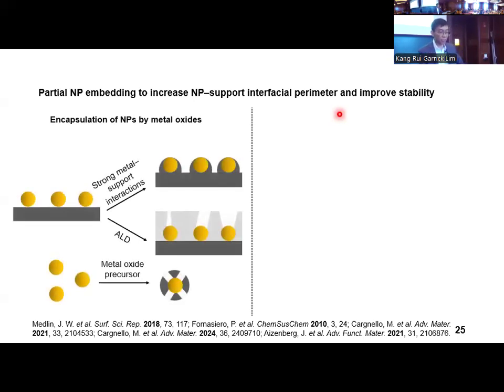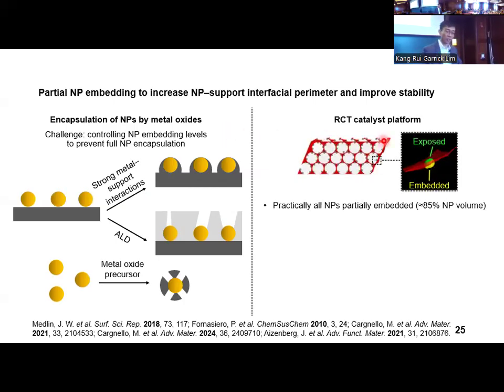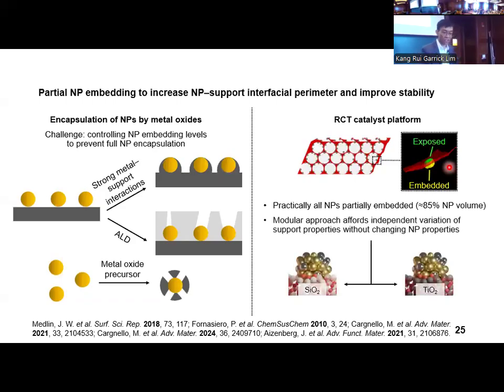Some synthetic strategies adopted by other groups to achieve this embedding feature include metal oxide migration by strong metal support interactions, or metal oxide overgrowth through dry or wet chemical means. One common challenge in these strategies is to devise synthetic ways to control the nanoparticle embedding levels while preventing complete nanoparticle encapsulation. Here, we use the RCT catalyst platform, as practically all the nanoparticles are partially embedded within the support. Moreover, the modular RCT approach affords independent variation of support properties without changing the nanoparticle properties, which cannot be achieved using existing catalyst preparative methods.